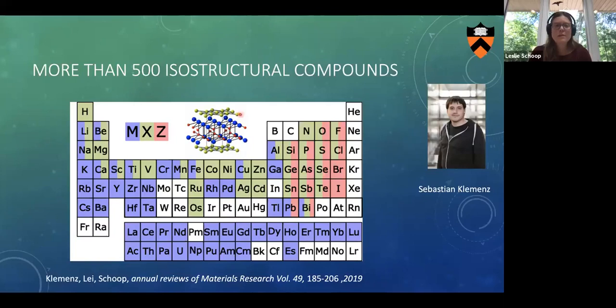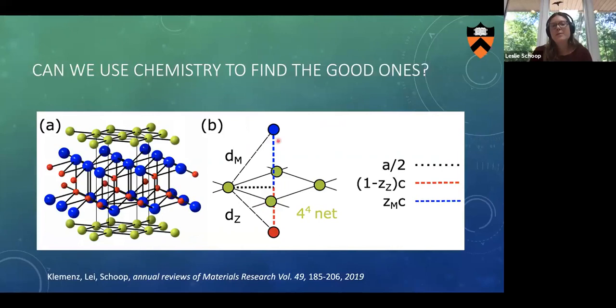So let's go to the second toolbox we have in solid state chemistry, which was related to sizes. But now I don't want to look at ionic radii. I want to look at bond distances, which is also some kind of measure of size of atoms. And so the hypothesis is, if this is really a delocalized chemical bond in the system that drives this interesting electronic structure, then I will have a shorter distance between the atoms in this net than to the next atom above and below. So why is this? A chemical bond always reduces bond distances, right? Because it bonds the atoms closer together and pulls them together. So I can just define that this distance is supposed to be smaller than the distance to the next atom above or below.